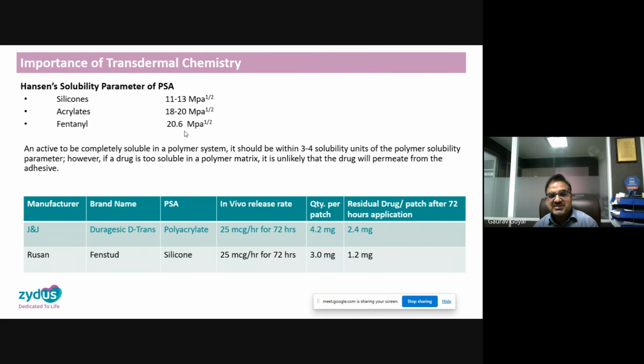and fentanyl 20.6. So if you see, fentanyl is somewhere near to acrylates, that means fentanyl has good solubility in the acrylates, and there is a gap difference of 7 between the silicones and fentanyl. So the solubility of fentanyl is less in silicones. So what happens if we make the fentanyl transdermal system in silicones? The problem is that maybe it will crystallize because the solubility of fentanyl is poor in silicones, but as fentanyl has a very close Hansen solubility parameter to acrylates, the solubility of fentanyl is very high in acrylates. So because of that, the problem of crystallization in the transdermal system with acrylates is least possible. So that is a good system, but